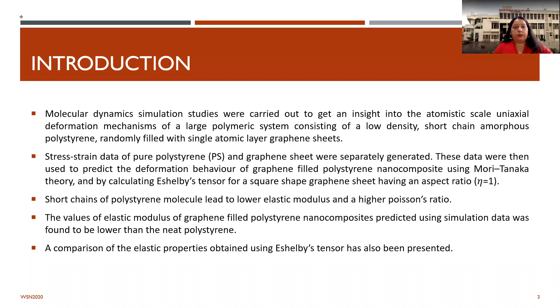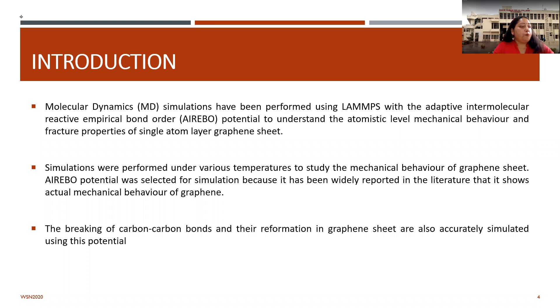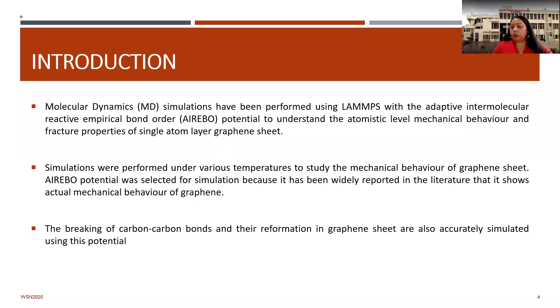Short chain polystyrene molecules lead to lower elastic modulus and high Poisson's ratio. The value of elastic modulus of graphene-filled polystyrene nanocomposite predicted using simulation data was found to be lower than neat polystyrene. A comparison of the elastic properties obtained using Eshelby tensors has also been presented. Before studying the graphene and polystyrene nanocomposite, simulations were performed on a single atomic layer graphene sheet and stress-strain behavior was predicted, found to closely match theoretical values. Deformation of graphene sheet at different temperatures was also predicted using simulation.